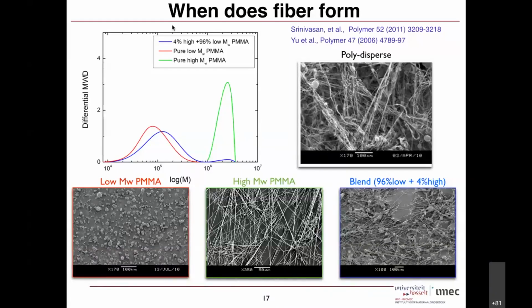So that's the thing that I told you, right? So when does a fiber form? Either you should have a very high molecular weight, the green color that you're seeing there, or if you have a red color one, which is a low molecular weight, then you should have a lot of concentration of polymer. But if you put too much polymer, then the viscosity will become very high. It will become like honey, and then you cannot pull the polymer down. But if you have low concentration, then you don't get the fiber.